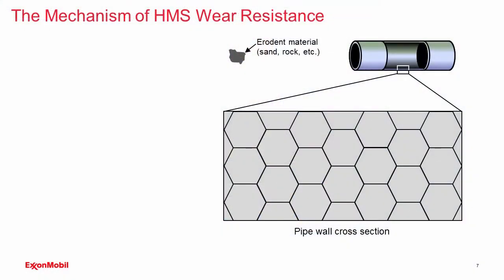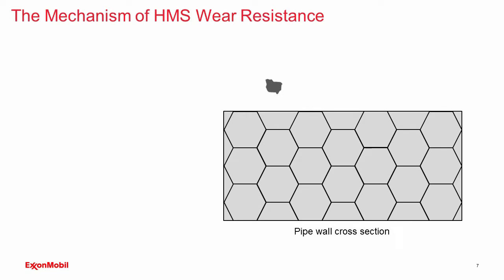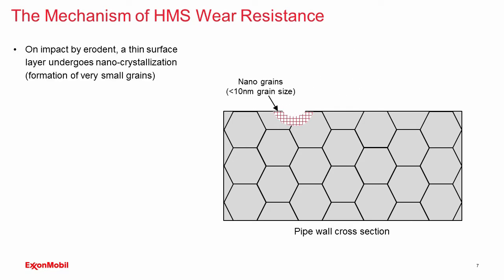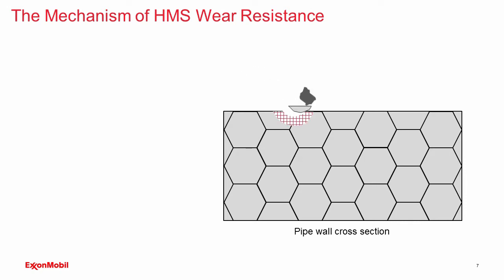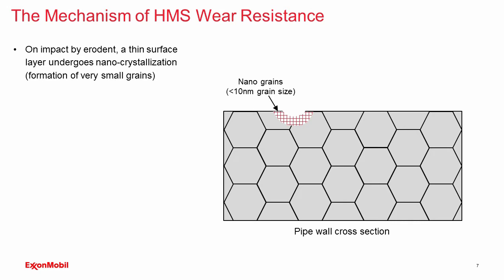Now, high manganese steels is a rather large family of steels, but there's a particular chemistry formulation, a particular grade that's rather good for wear resistance. So you can see there the cartoon cross-section of the pipe wall and then some erodent material like sand or rock. What happens when this particle strikes the surface is that a small region, and let me just show that one more time, a small thin region underneath the material that's removed, the impacted area, goes through metallurgical transformation and undergoes a nanocrystallization event, and the grain size is extremely small in that thin layer.